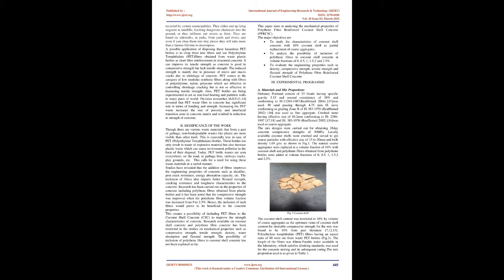It can improve its tensile strength, as concrete is good in compressive strength but lacks tensile strength. The reduced strength is mainly due to the presence of micro and macro cracks due to shrinkage of concrete. PET comes in the category of low modulus synthetic fibers, along with fibers of polyethylene, nylon, and polyester, which are effective in controlling shrinkage cracking but are not so effective in increasing tensile strength. Also, PET bottles are being experimented with to act as non-load bearing and partition walls in many parts of the world.